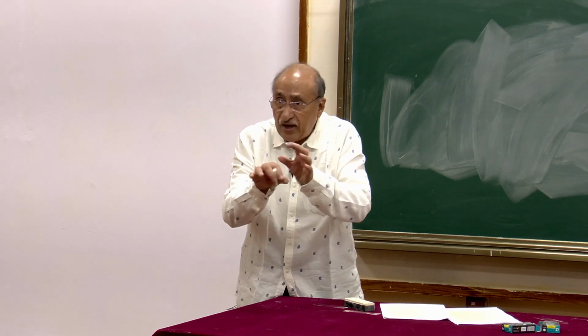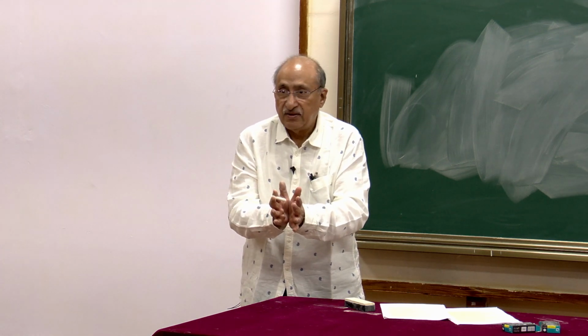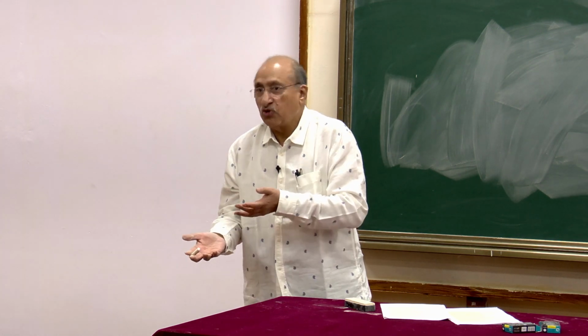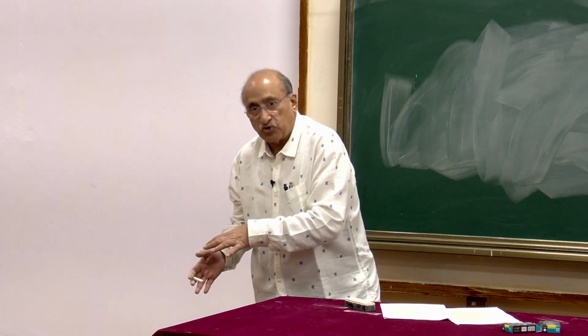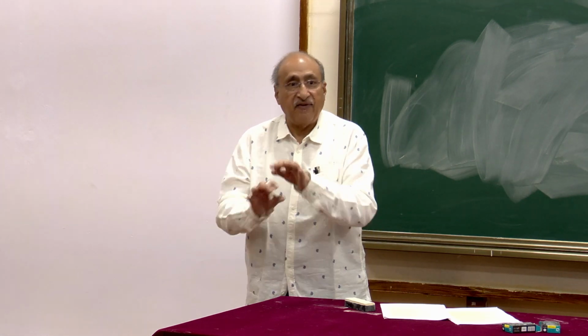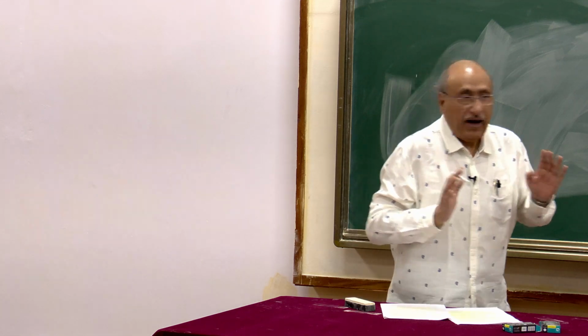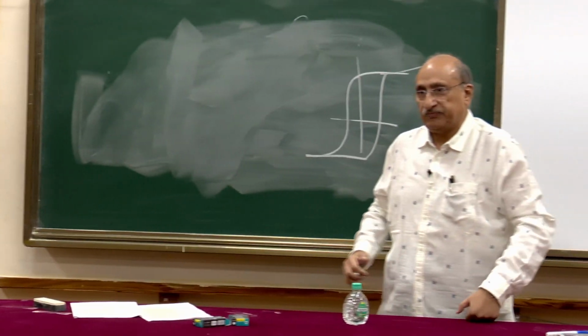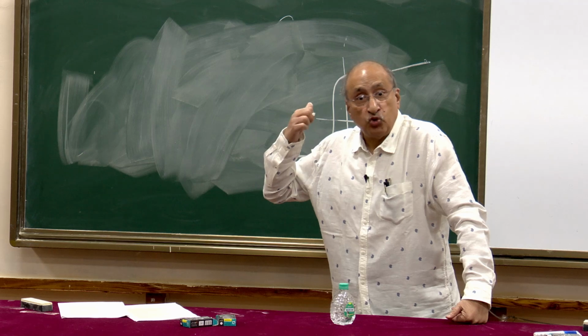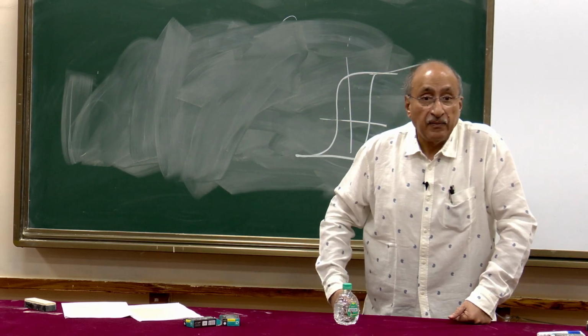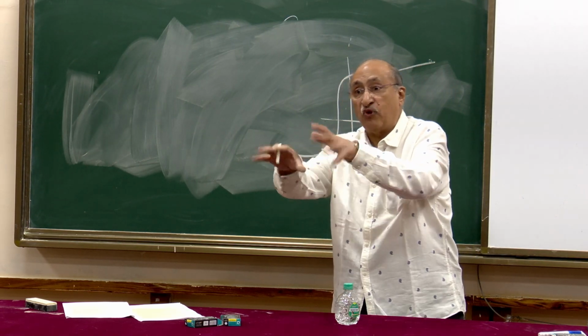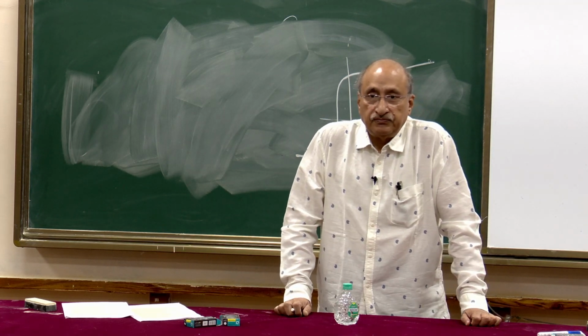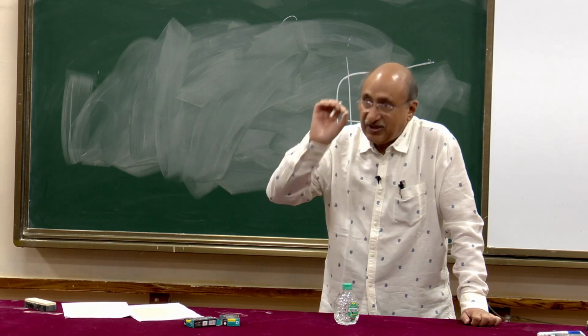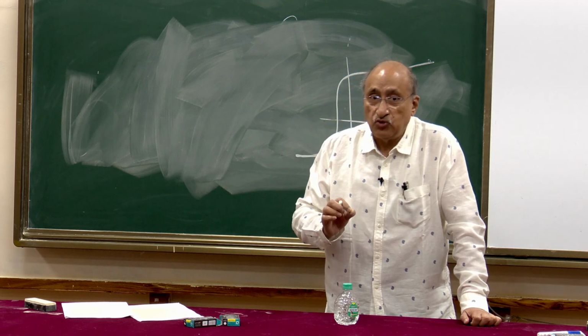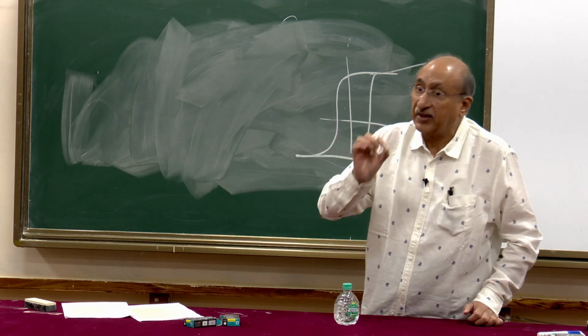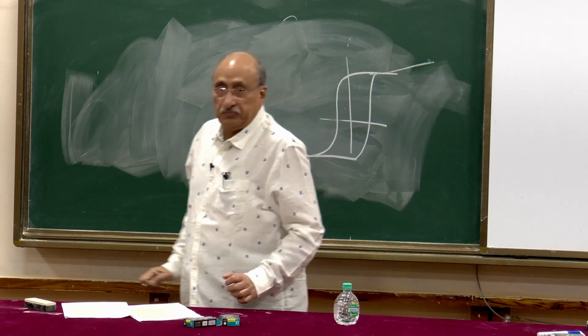This is because of the poorly magnetized region between grain boundaries. We are not sure whether we call them paramagnets, superparamagnets, or ferromagnets. They have some sort of odd structure, and you keep on aligning magnetic moments there. In fact, that's the reason that you do not get even the 4 pi M value that you got in the bulk, because there is a significant amount of material which is in that poor state. My next talk tomorrow will start with this statement: whenever you are talking of thin films, you generally find magnetization to be significantly smaller than the bulk value because of this particular problem.